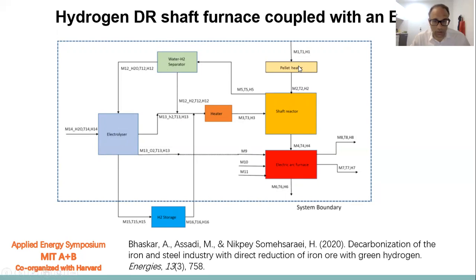This is not to overcome this threshold of 800 degrees, because above 900 degrees we could have sintering. And then, as we said, we have electric arc furnace.